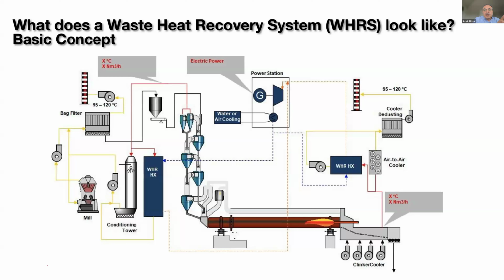So as I said, 30 to 40% of the total heat input in the system is wasted through the hot gases, either coming out from the preheater or from the cooler, in the form of radiation from the hot surfaces and so on. Waste heat recovery has been looked at for cement manufacturing, other than the thermoelectric generator that we are talking about here. In the past, there have been, and still in use, the steam Rankine cycle or organic Rankine cycle and so on. Basically, the equipment that we need is a heat exchanger that takes the heat, and this heat exchanger is next to the preheater tower.